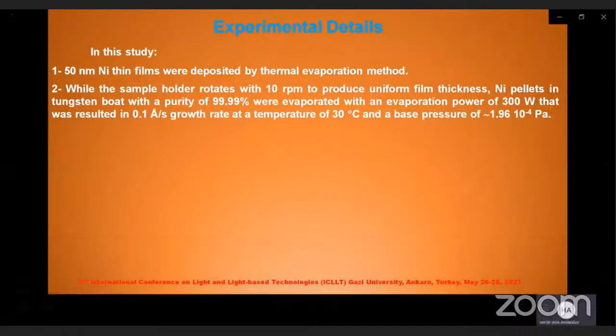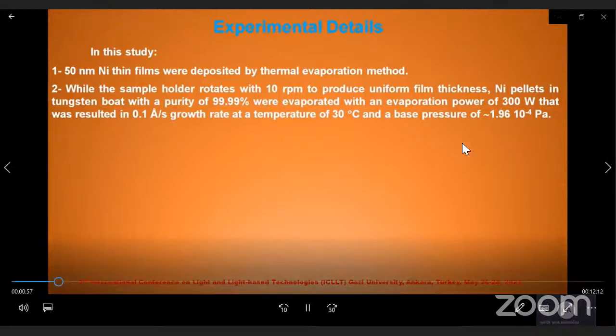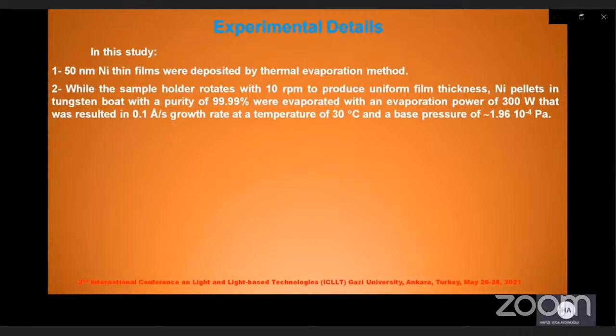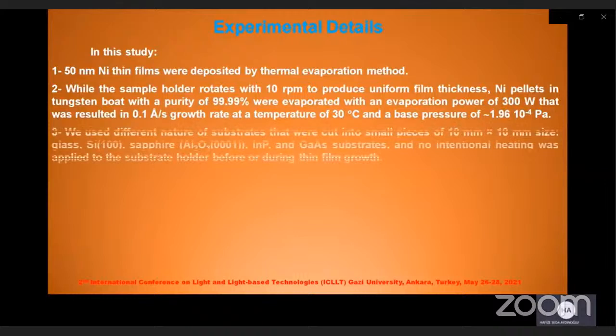Nickel pellets in a tungsten boat with a purity of 99.99% were evaporated with an evaporation power of 300 watts. That resulted in a 0.1 angstrom per second growth rate at a temperature of 30 degrees and a base pressure of approximately 1.96 times 10 to the minus 4 Pascal.